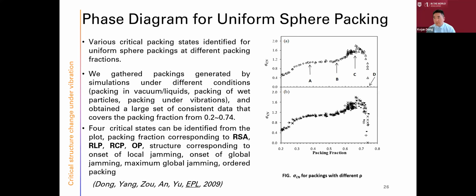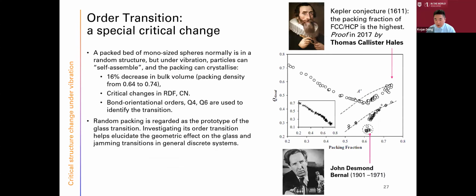And as I previously mentioned, we collected lots of packings, and we identified several packing critical states, critical structure change points. And one particular critical change is that when the packing fraction goes beyond 0.64, it will have to crystallize, changing to the ordered packing.